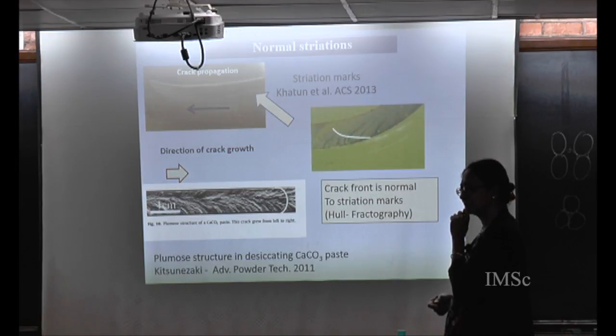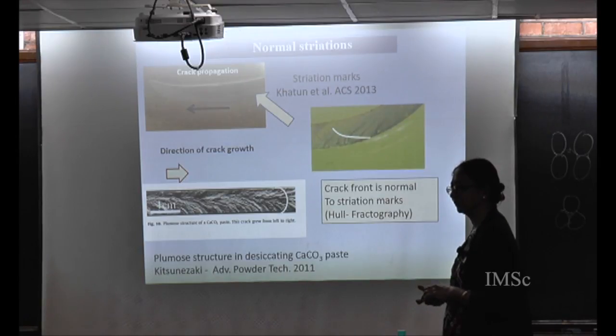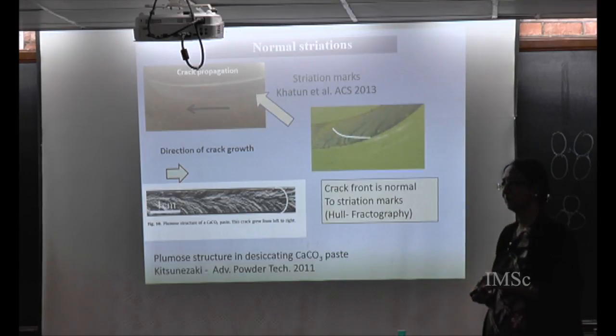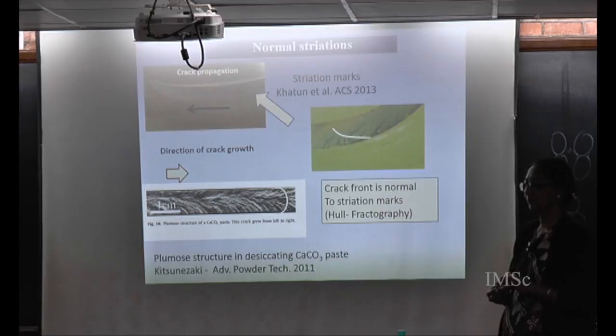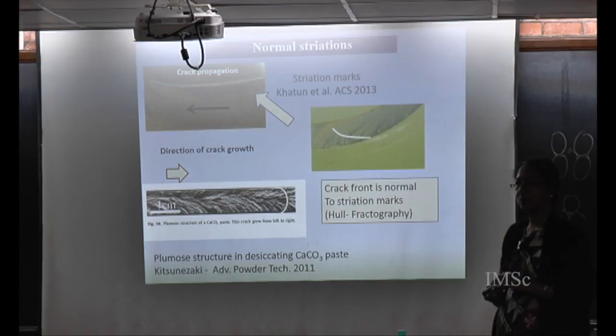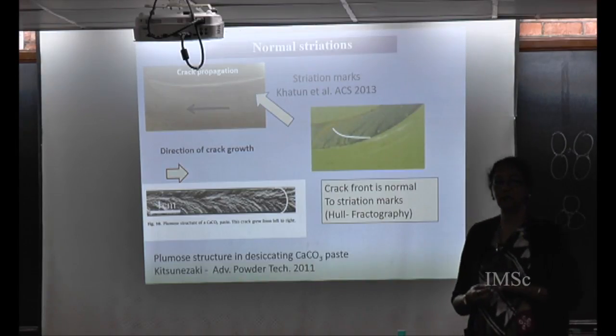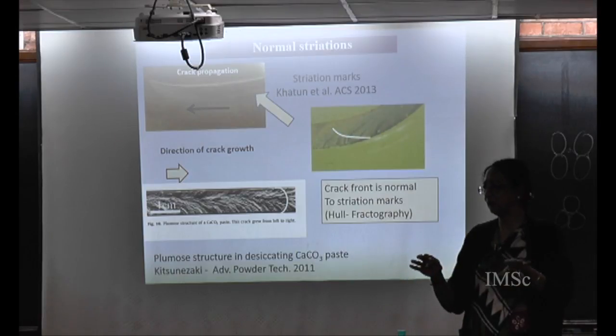So at least in PMMA, which is driven in subcritical growth with pinning centers, what we observe is these lines that correspond to the front when it's pinned. And then if you have an instability in speed, if the system, like how gamma depends on V, drives you to an instability from going slow to fast, you can then have something that leaves lines. To understand that, we should try to do the Perspex experiment in mode 1.